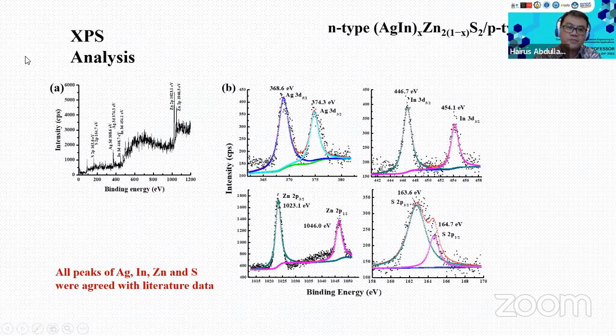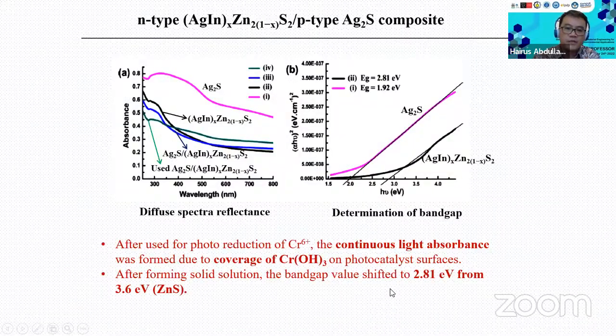Okay, then just to show you the XPS analysis, we have all the elements, and also the binding energy of each element in the PN heterojunction. The next one is to show you the DRS before and after use in the photocatalytic reaction. It seems the optical absorption is degraded because some of the chromium trivalent is attached on the surface of the catalyst and makes the optical absorption decrease.